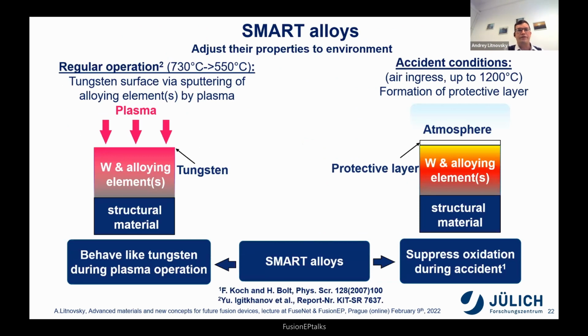And this is actually the basis of the smart alloy concepts. These materials are designed to be chameleons, which really change their properties depending on the environmental conditions. The material itself detects these conditions. During regular plasma operation, the tungsten alloy, which is alloyed with special alloying elements, chromium and, in our case, yttrium, which are lighter, will be sputtered by the plasma almost immediately, leaving a pure tungsten surface facing the plasma. And this is what the plasma actually needs: low sputtering, low tritium retention, and all other advantages, such as the high melting point of tungsten. So the tungsten protects the underlying elements from the plasma. It will be the protecting layer.